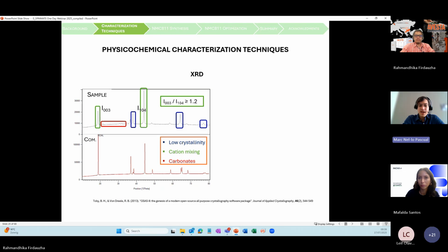You can also estimate the cation mixing by the intensity of the higher intensity peaks of the NMC, that are the ones located in the Miller index positions 003 and 104. If you divide those intensities, you should be getting around 1.2 or a higher value. If you are below this value, you know that there's a significant cation mixing that should be 10% or higher in those samples. And last, even if it's not the best technique, if there's a huge amount of carbonates, you can see them in this position between 20 and 42 theta, that is where there are signals with high intensity. However, this is just for looking at the patterns.